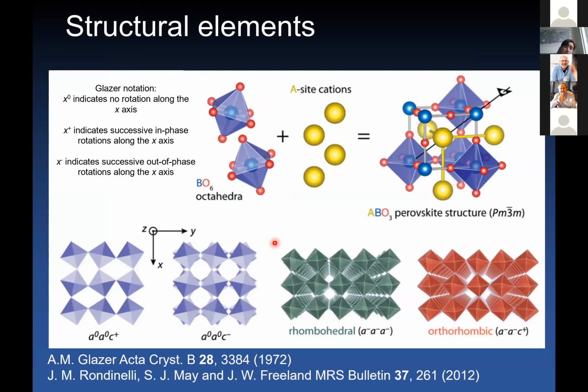And it is useful to classify these structural distortions according to the Glazer notation. So we focus here on the patterns of oxygen octahedral rotations that are realized in these materials. If you look at the literature, you essentially see that you have three types of symmetries that are realized often at low temperatures: either a tetragonal phase, a rhombohedral phase, or an orthorhombic phase. And these are characterized by either no rotations of oxygen octahedra, in-phase rotations, or out-of-phase rotations of oxygen octahedra along a specific axis.